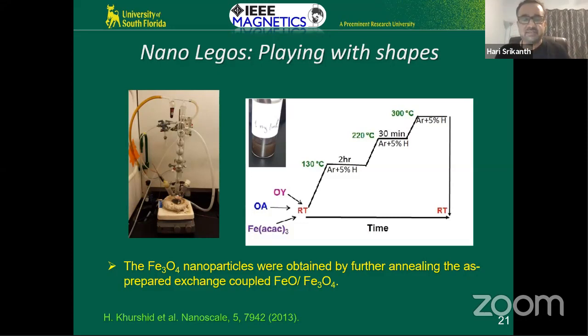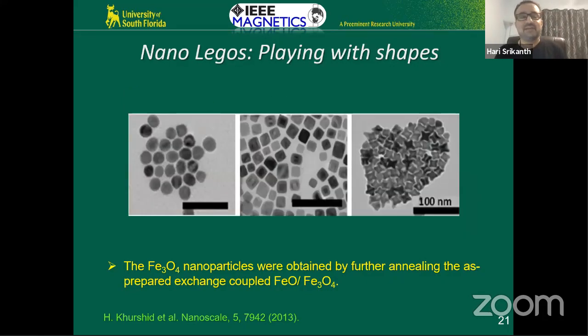She came to me and said, but Srikanth, aren't we supposed to play with the shapes? I said, yeah, well, it's already difficult to make these core shell particles. I don't know how you would play with the shape, but go ahead. She went ahead. I'm glad that I said, do it. She came back with this set of samples. She was able to controllably change the particle from roughly spherically symmetric to cubic to these exotic star-shaped. And again, if you see, the anisotropy is increasing. In this case, we're talking about surface anisotropy of these nanoparticles going up. So we can immediately check what the effect on SAR is.